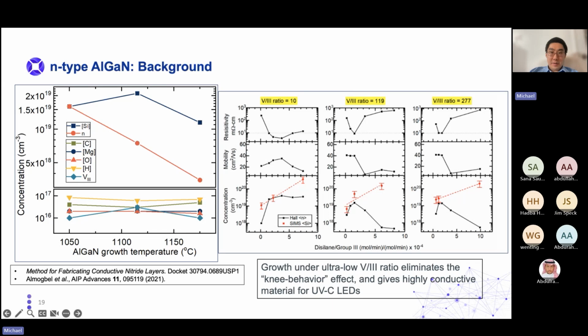What Dr. Abdullah Al-Meghbul discovered was that if you decrease the V/III ratio all the way down to an extreme like 10, this knee behavior widens dramatically, so the resistivity drops off, but then stays very low for a wide range of silicon flow. And the same trend can be observed in the mobility and carrier concentration. So in the carrier concentration, with normal high 5:3 ratios, it would drop off extremely quickly with more silicon flow, but with ultra low 5:3 ratios, this carrier concentration would stay flat with more silicon flow.